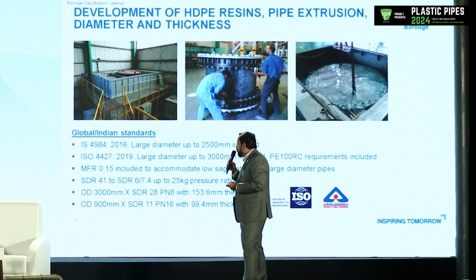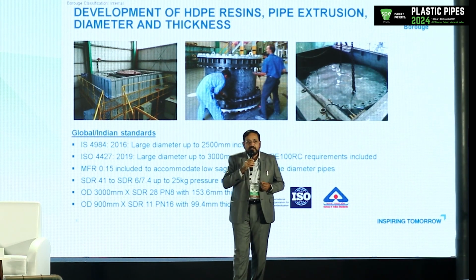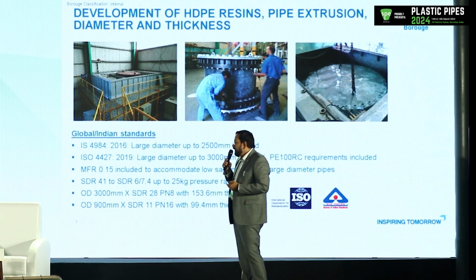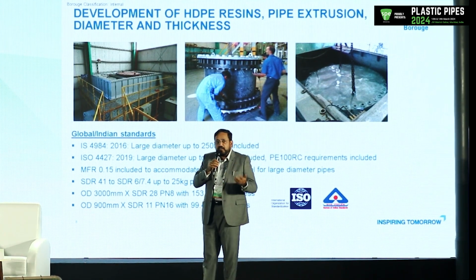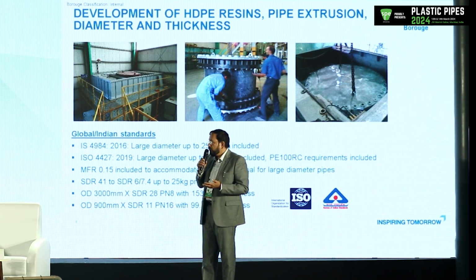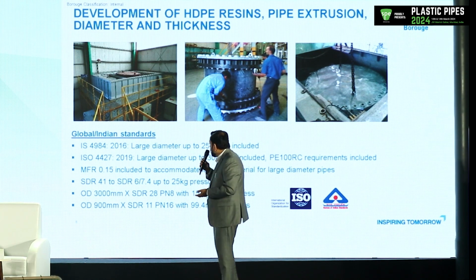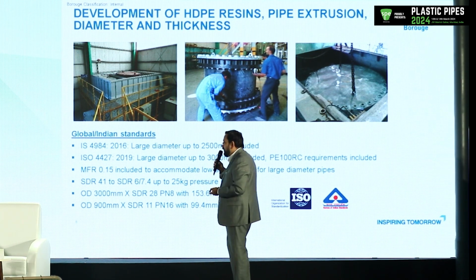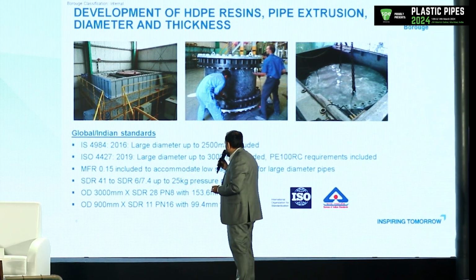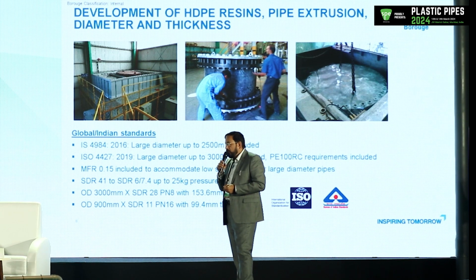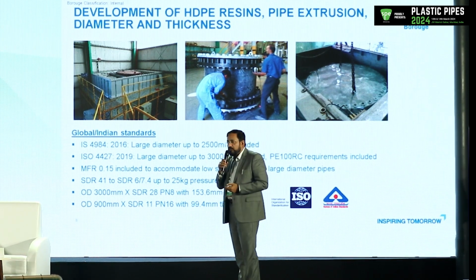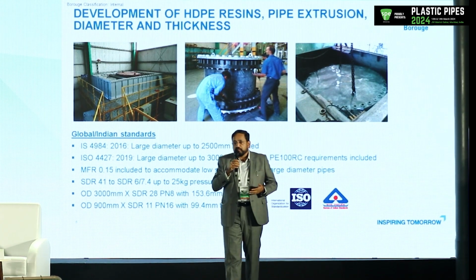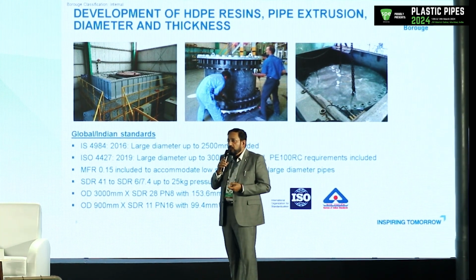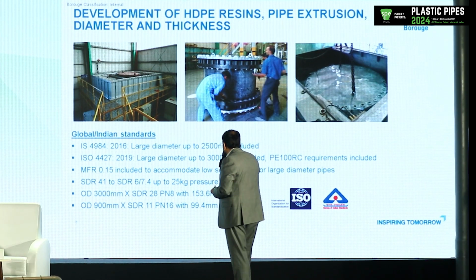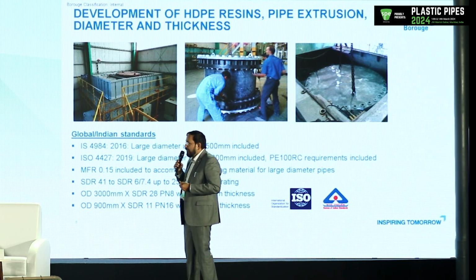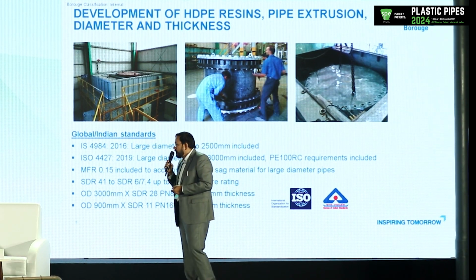Is it only the raw material and the testing? No. The standards are also getting aligned internationally. The Indian standard has been raised because Jain Irrigation started producing the 2,500 pipe, and so the Indian standard also increased the range from 1,600 to 2,500. ISO 4427 had gone to 3,000. To accommodate producing such larger pipes, you need a change in the MFR range. From 0.2 it has come to 0.15. This is done not only in ISO, but also in the Indian standard.